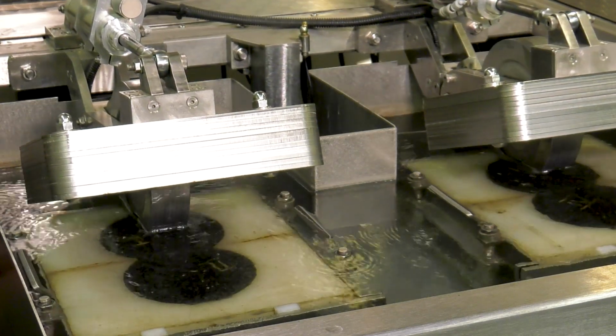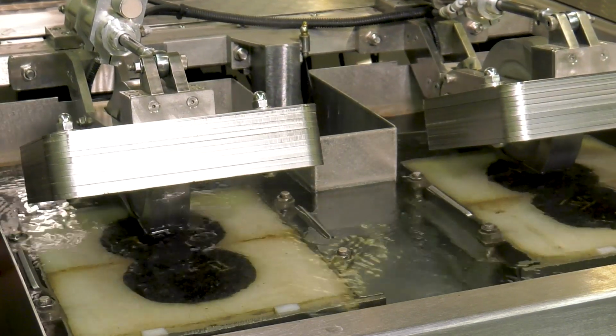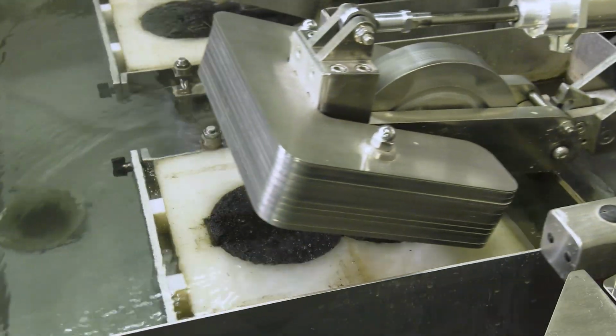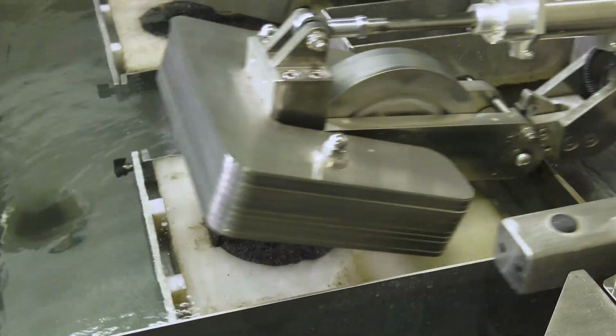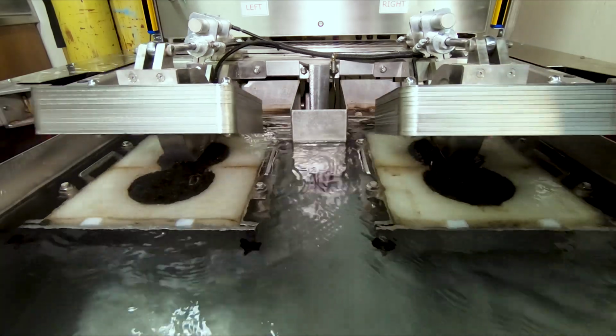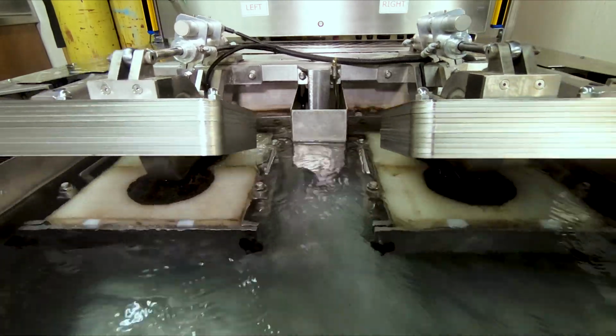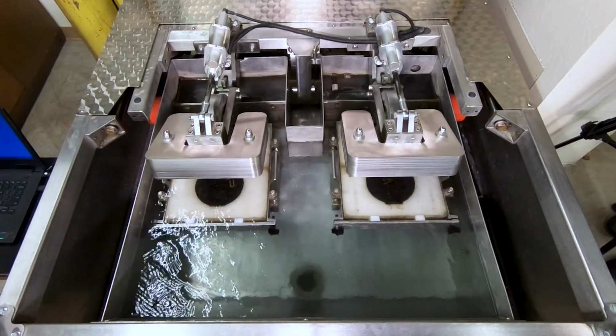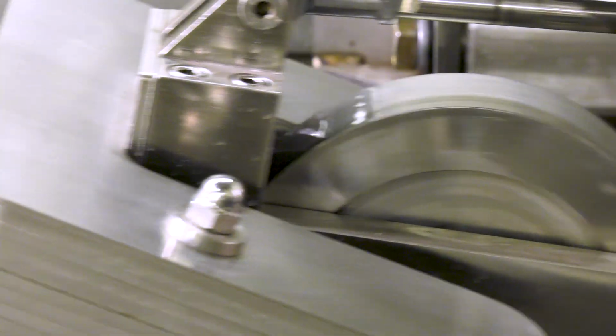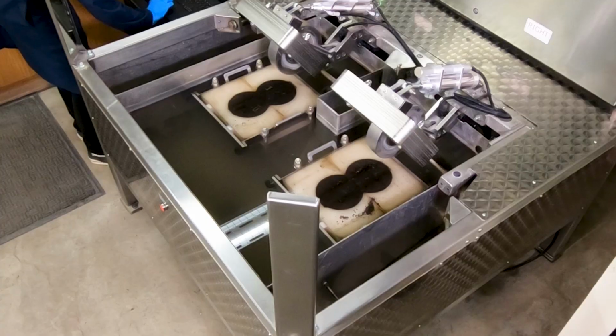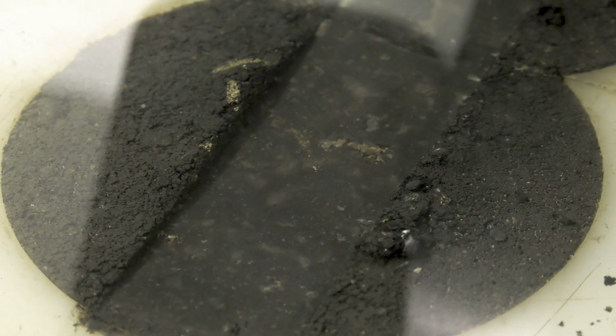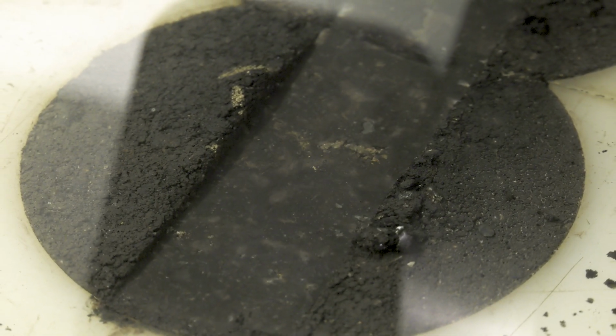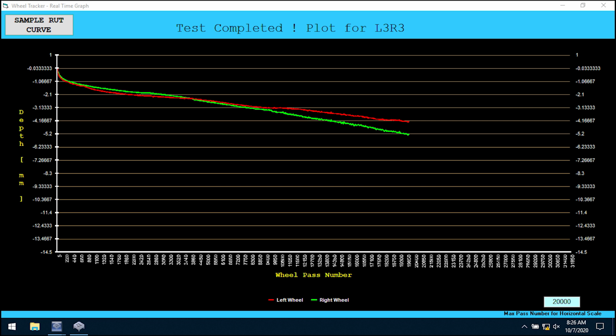Run the test for either the specified number of cycles, typically 20,000, or threshold rut depth. The test should operate with a smooth movement across the test specimen. At approximately 52 cycles per minute, a 20,000 cycle test will last about 7 hours. The wheel tracking device will stop at 20,000 passes or when the test has reached the maximum rutting depth. The device software automatically saves the test data file.